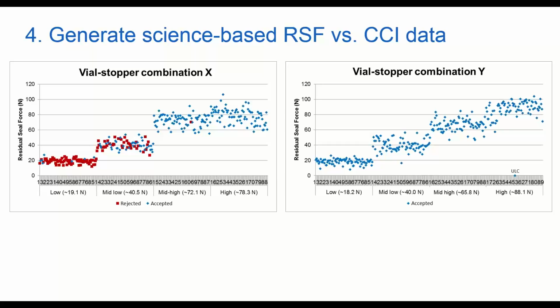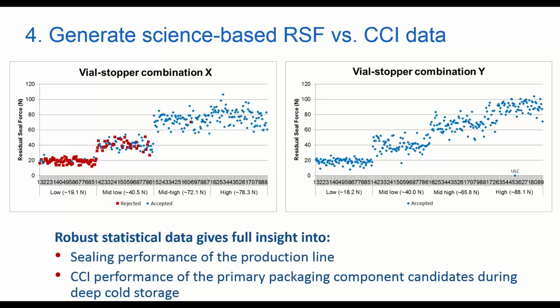And the red data points are samples that lost CCI after deep cold storage or during deep cold storage. And so you see that for the first vial stopper combination, if it's loosely or even nominally capped and crimped, you get a high number of failures. Once you reach tightly capped and crimped, those samples are holding good CCI. For vial stopper combination Y, you actually see good CCI over the full range of RSF values. So clearly a more robust vial stopper combination when it comes to deep cold storage, also as a function of the vial sealing. And again, the key here is to have robust statistical data giving full insight into sealing performance of the production line. So you get insight into your process, but you also want to get that correlation to CCI performance of the primary packaging components in the deep cold storage.